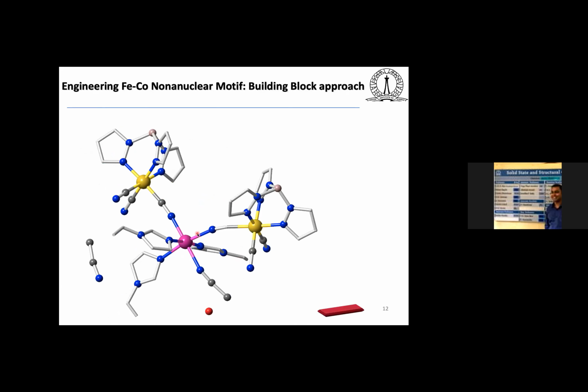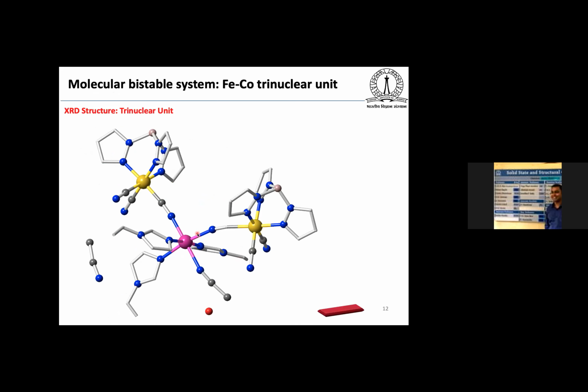Then we have, apart from the single crystal XRD, so for the red crystal, we got this trinuclear unit, where you can see this cobalt 2 is bound with the two different iron metals, iron building block, and you have acetonitrile and water as the crystallization solvent molecules.